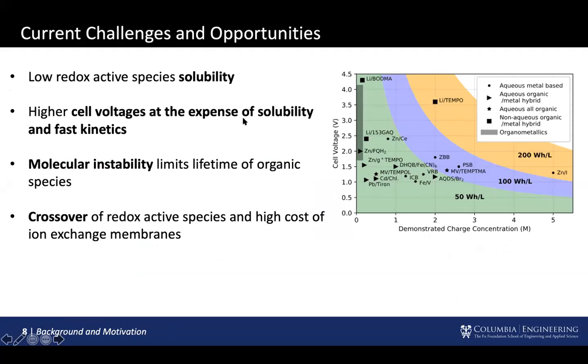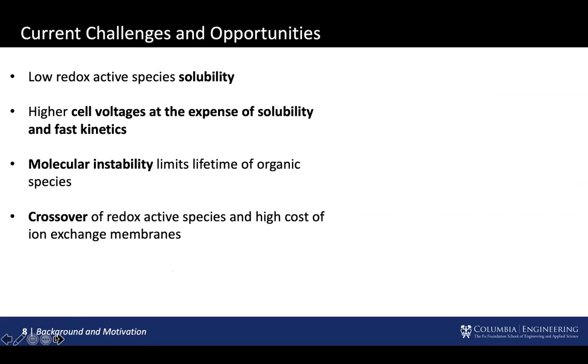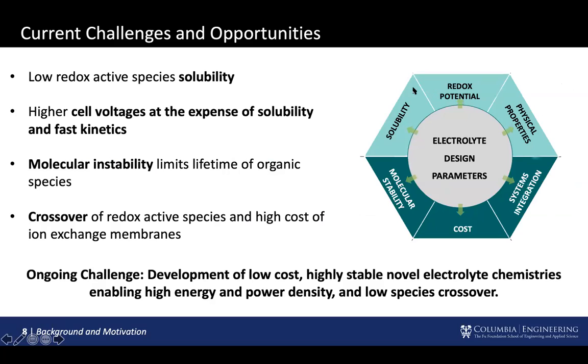So we've seen that solubility is an issue, as well as this issue of cell voltages and solubility. There's a trade-off there that I'm trying to get across in this image. We see that we can tune the cell voltage to increase energy and power density. Non-aqueous electrolytes can achieve that. But at the same time, that comes at the expense usually of lower solubility in those systems. So that sets the ceiling of energy density that we see here. We're basically beginning to see that there are trade-offs between all of these parameters.